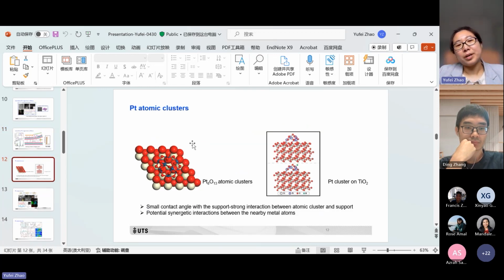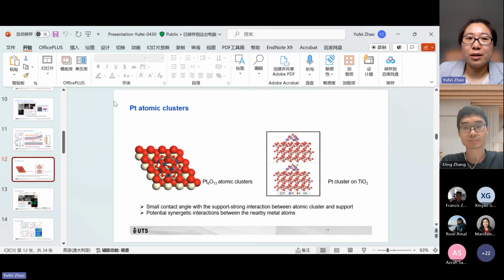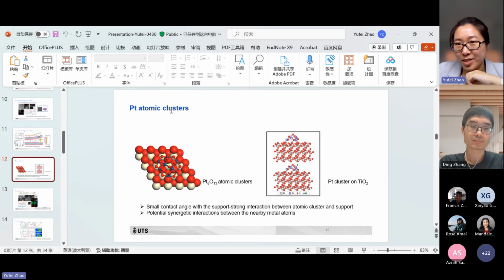For the atomic clusters, we have worked on platinum atomic clusters and also ruthenium and iridium atomic clusters. For our material, we have tested it in both acidic and alkaline conditions. The platinum shows slightly better performance in acidic compared to alkaline conditions. But for the ruthenium atomic cluster, it shows quite good performance in alkaline conditions.